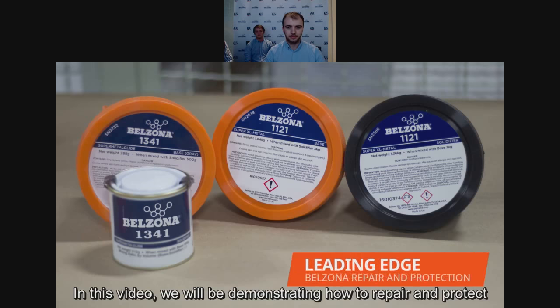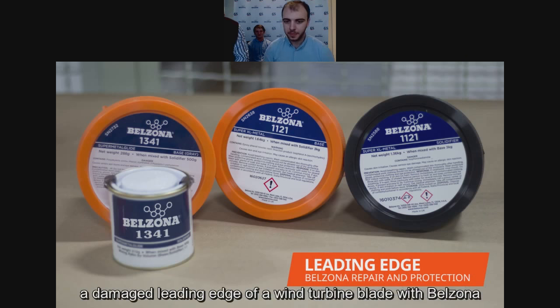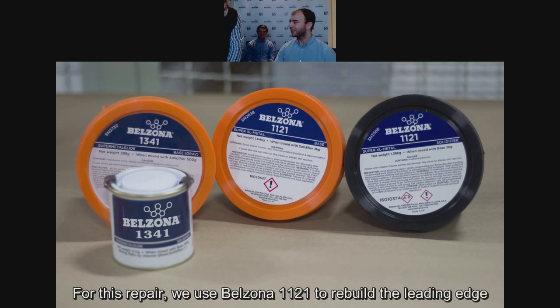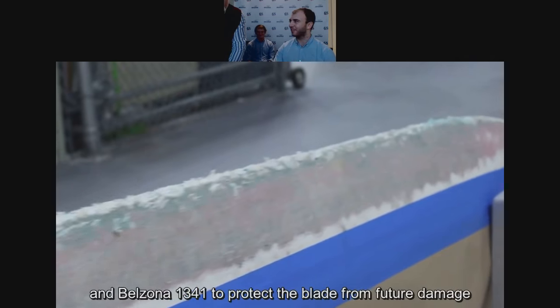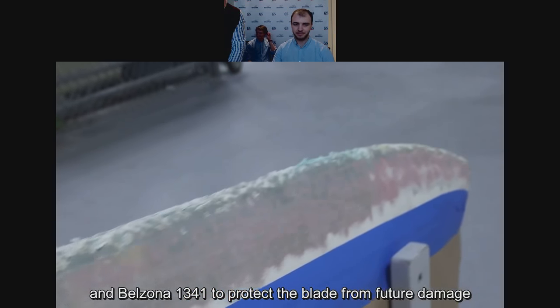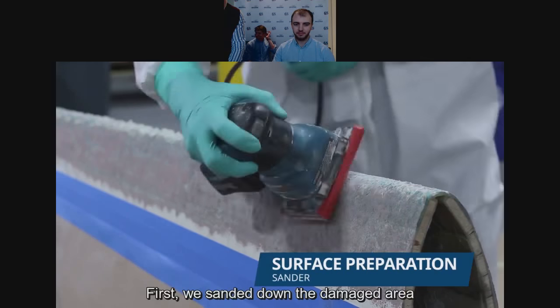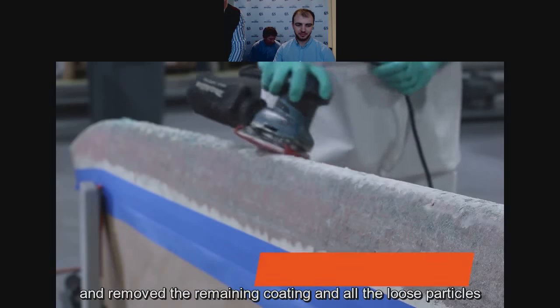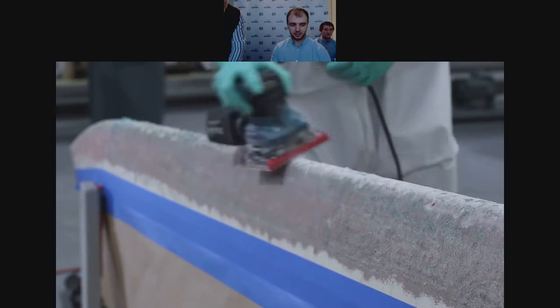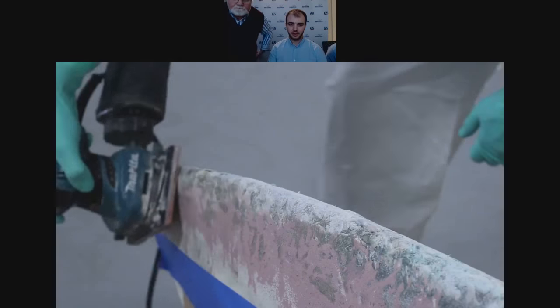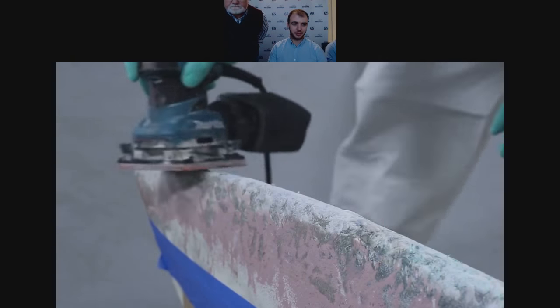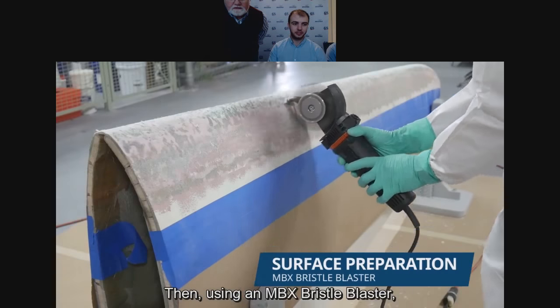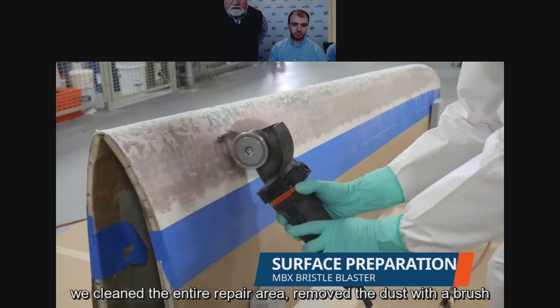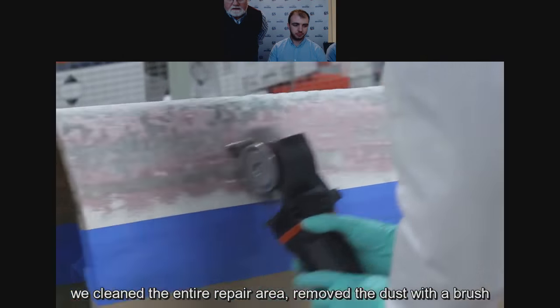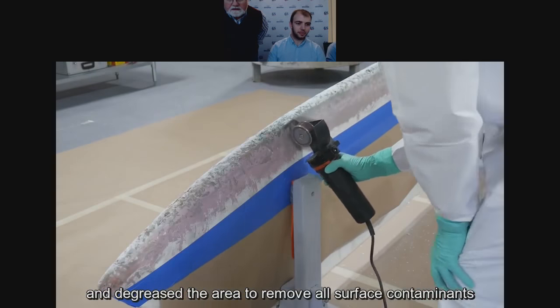In this video, we will be demonstrating how to repair and protect a damaged leading edge of a wind turbine blade with Belzona. For this repair, we used Belzona 1121 to rebuild the leading edge and Belzona 1341 to protect the blade from future damage. First, we sanded down the damaged area and removed the remaining coating and all the loose particles. Then, using an MBX bristle blaster, we cleaned the entire repair area, removed the dust with a brush, and degreased the area to remove all surface contaminants.